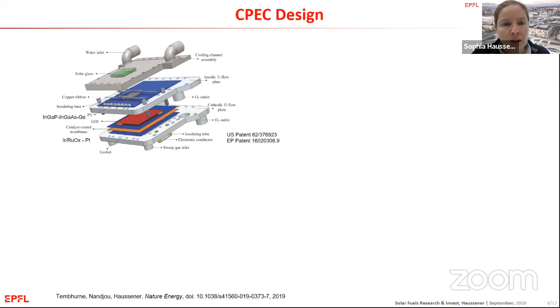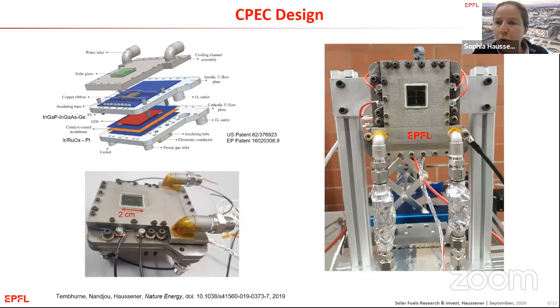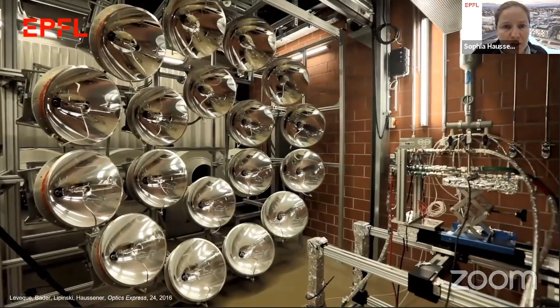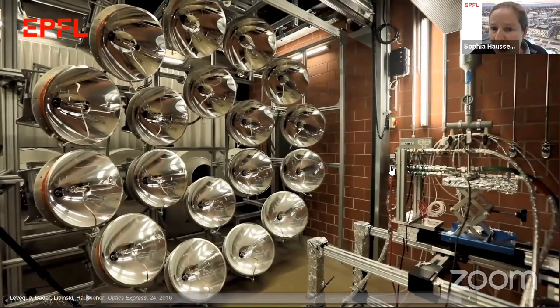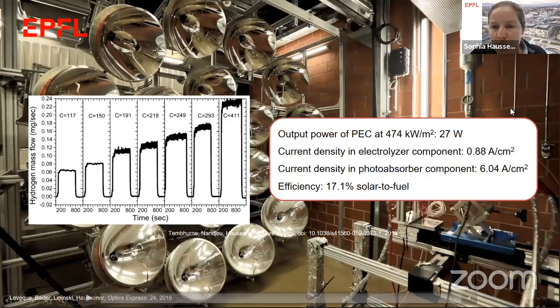And here you can see the actually built design, and then put into the focal spot of our high flux solar simulator. So the simulator is approximating concentrated radiation. Here you see the device from the back side. Photoactive area is 2 by 2 centimeters. And with this, we were able at about 474 times concentration to produce an output power in terms of hydrogen produced of about 30 watts at current densities that are in the order of magnitude of commercial electrolyzers. And we did this at a reasonable efficiency, 17%.